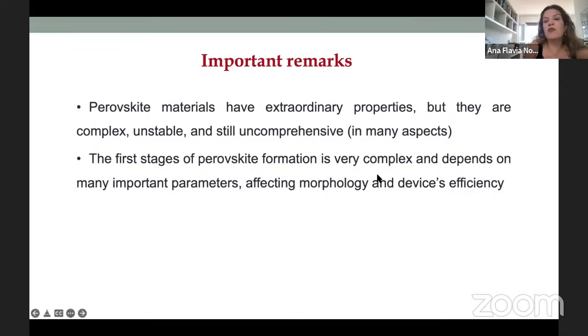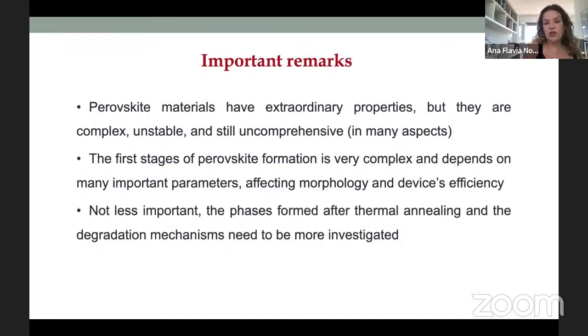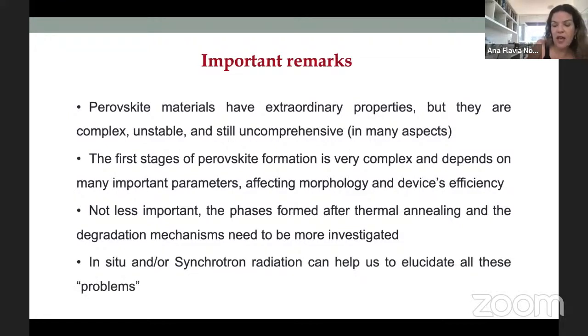The first stage is the perovskite formation, even in solution, and the film is very complex. It depends on many, many important parameters. And all of this is going to affect the morphology and device efficiency. That's the reason it's important to look at the first stages and the formation of these materials. Not less important, we also need to understand more about the degradation. As I mentioned before, in the golden triangle, we still need to improve the stability. And I think with these operando experiments that we are going to do right now in the Carnaúba, we can get more information about this kind of degradation. And here, this is my message. The synchrotron is here in Campinas.